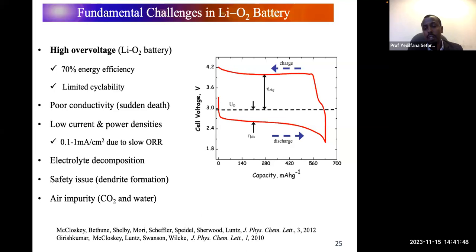So the conductivity issue is also there. Lithium peroxide is a large band gap material with over 4 electron volts. And the side product, which is lithium carbonate, is even worse. It's around an 8 electron volt band gap material. So the conductivity should be improved, and we'll apply the same mechanism as we apply in metal ion batteries. The electrolyte decomposition is also an issue. A slow oxygen reduction reaction at the cathode side is again a problem that results in low current and power densities.